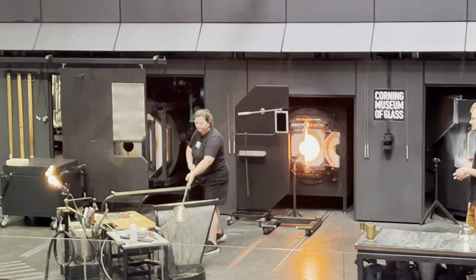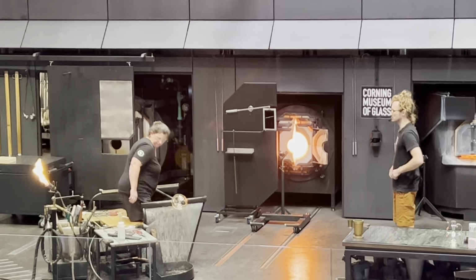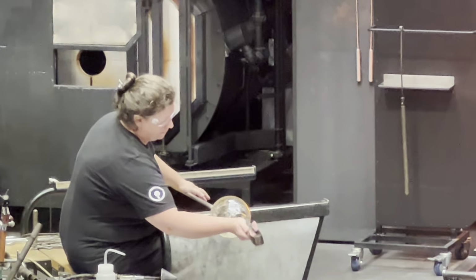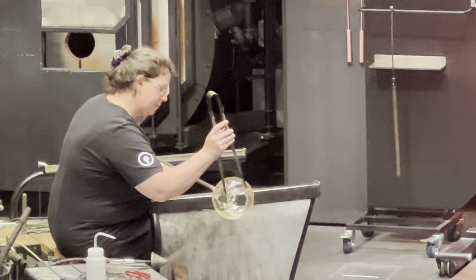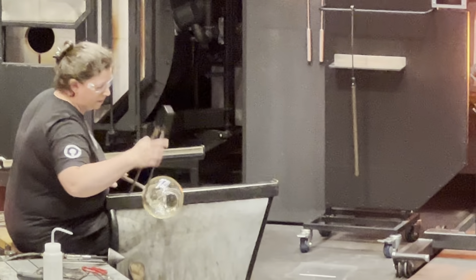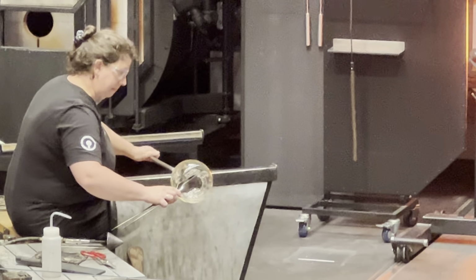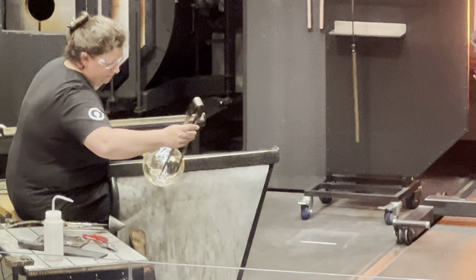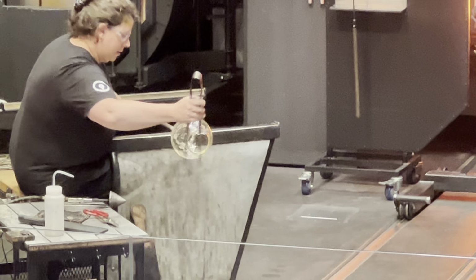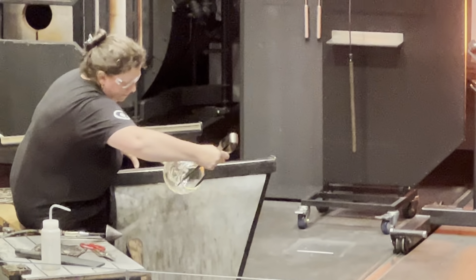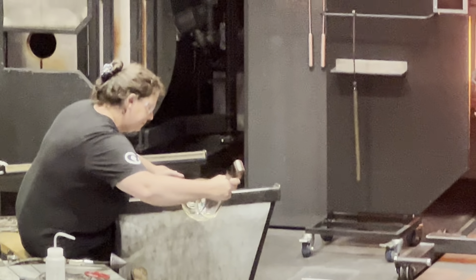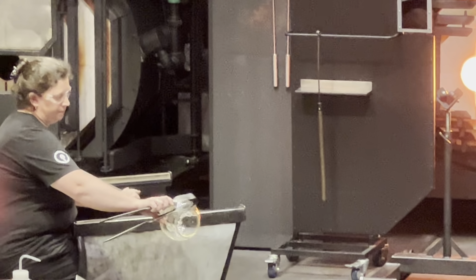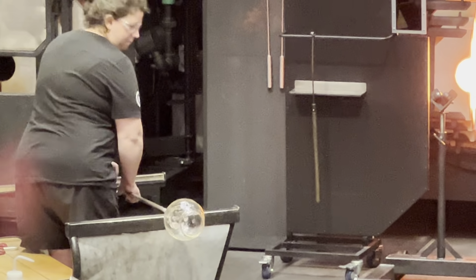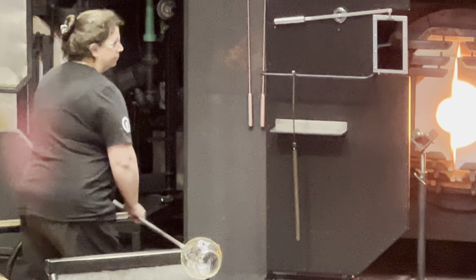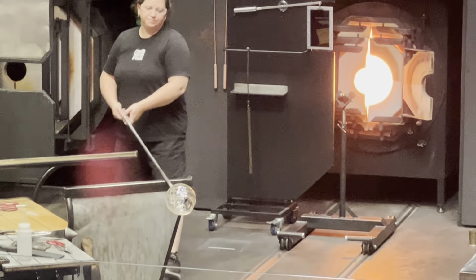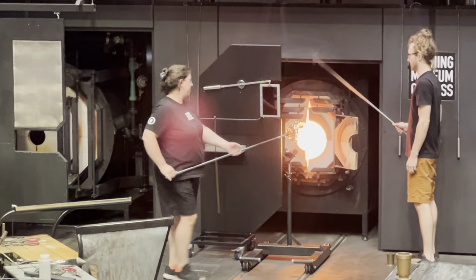Now, Catherine's also focusing heat on just the part she wants to change, so just the very top, where she plans to open this up to be a bowl. Every once in a while, she does put the glass into the reheating furnace, all the way into the reheating furnace, to maintain temperature all the way back at that punty connection. That glass is stuck onto the punty again because of the temperature, and if we let it get too cold, it can fall right off the end of the pipe. But she's folded the lip back onto itself. She opened it, rolled it over onto itself to create a little ring of double thickness.